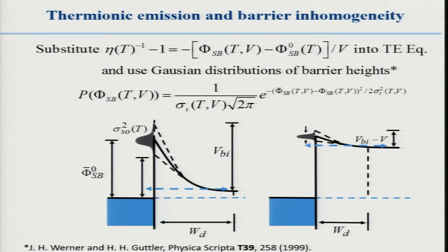How do we analyze this? This was done in the old days by Werner and Gutler, not too long ago. But since we can go down to lower temperatures, we can get the temperature dependence of our idealities and our zero voltage Schottky barrier heights to a lot lower temperatures. And the way we analyze it is similar to what Werner and Gutler did: you assume that there's a distribution of barrier heights. That's reality.